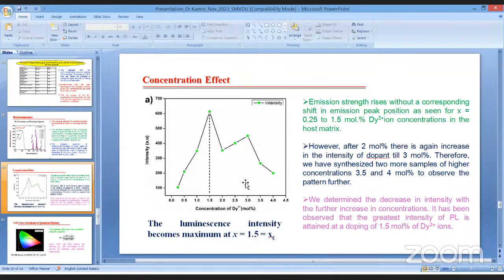So you can see here I have plotted the concentration effect. The concentration versus intensity is shown here. You can see emission intensity basically rises, without a corresponding shift in emission peak position, from 0.25 to 1.5 mole% dysprosium ion concentration in the host matrix. After about 2 mole%, there is again an increase in the intensity of the dopant till 3 mole%. Therefore, we have synthesized 2 more samples of higher concentration, 3.5 and 4 mole%, to observe the pattern further. And we see a decrease in intensity with the further increase in concentration. It has been observed that the greatest intensity of PL is attained at doping of 1.5 mole% of dysprosium 3+ ions.